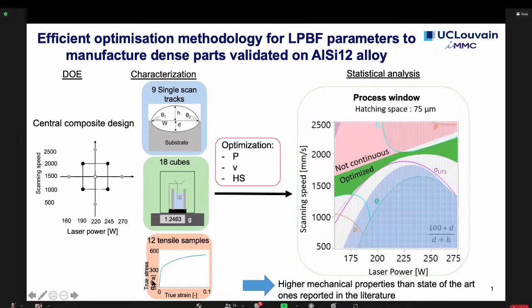Then we took the results of all these three steps, and it enabled us to build a statistical model, which is able to predict all these results, so the density and the mechanical properties, as a function of the LPBF parameters. We can see here that in green, we have the optimized parameters. With these optimized parameters, we could compare the experimental mechanical properties and density with the ones predicted by the model, and it was in really good agreement.